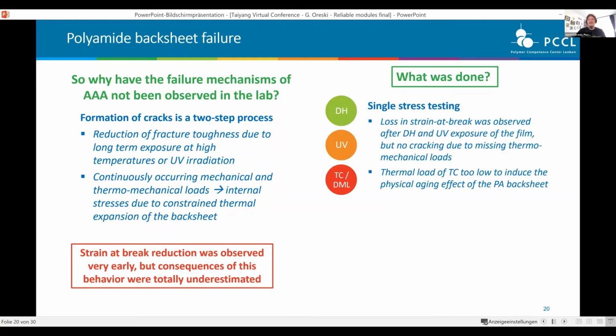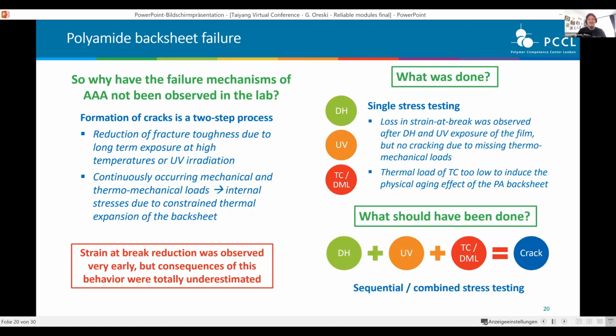The problem, we did single stress testing. So they did proper testing, several thousand hours of damp heat and UV exposure of the film, but there no cracking was observed because there was no thermomechanical load on the sample. Then they did modules, but they put one module in damp heat, one module in UV, one module in thermal cycling. In any case, no cracks appeared because what was missed, what should have been done was to put the module first in damp heat, then in UV, and then put some mechanical load on it, then the crack will appear. So you should do some sequential or combined stress testing.